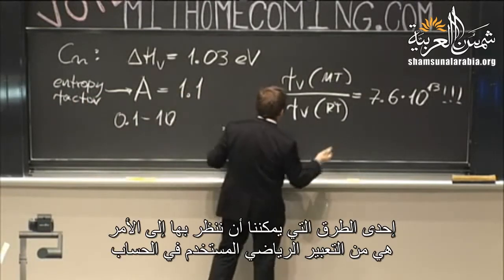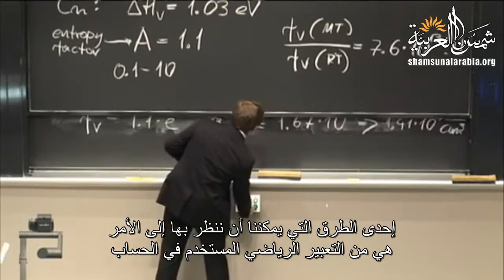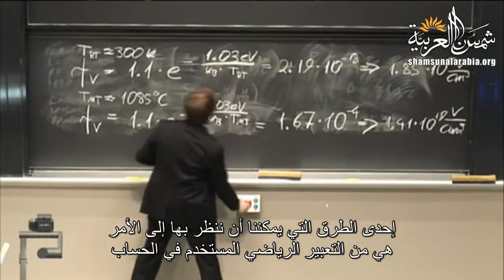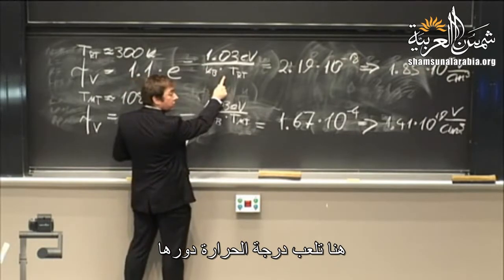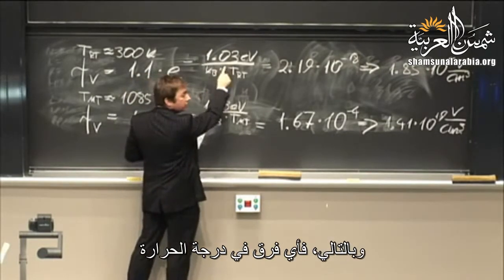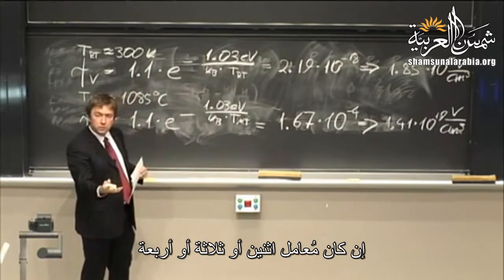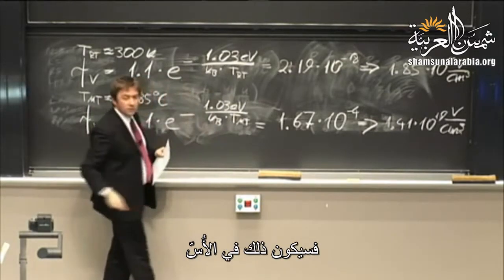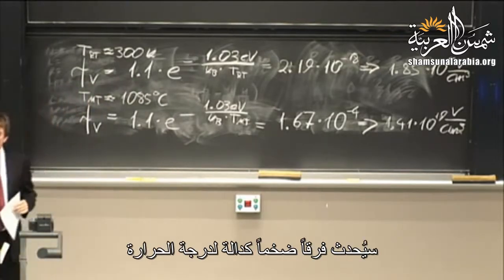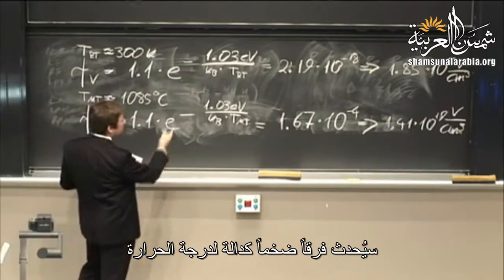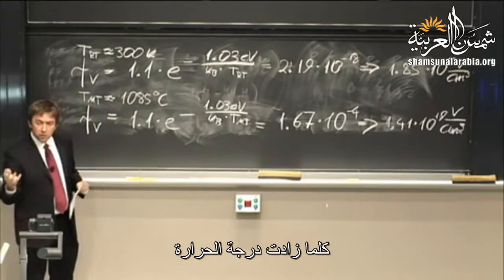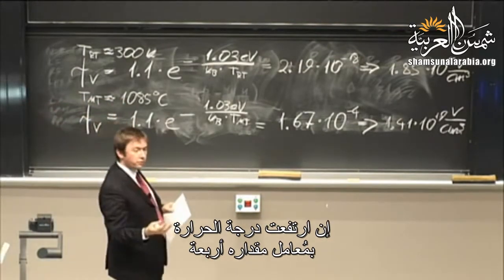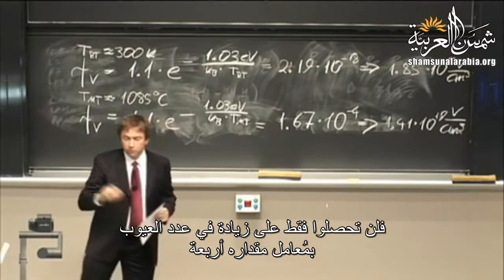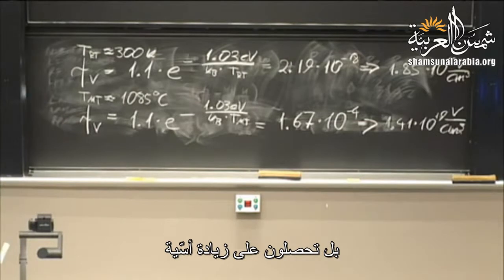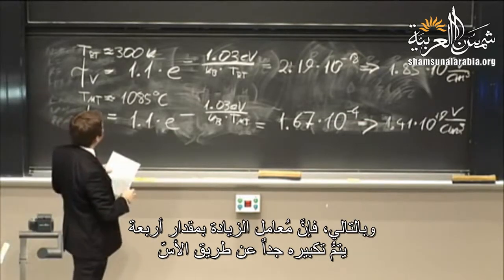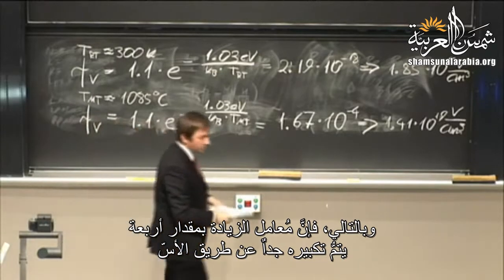Why is that? Well, one way to look at that is just from the expression that we have to calculate the number. Here's where the temperatures go. So any difference in temperature, if it's a factor of 2 or 3 or 4, is going to go into the exponential. So that exponential is making a huge difference as a function of temperature in terms of the number of defects that you get. If you go up a factor of 4 in temperature, you don't just get a factor of 4 increase in the number of defects. You get that in the exponential, so the factor of 4 is hugely magnified by the exponential.